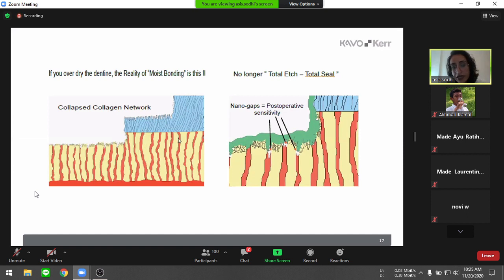It will not percolate. That means that there can be gaps that are left on the dentine surface where the bonding agent has not been able to percolate and seal those gaps. And these nano gaps cause post-op sensitivity, right? So this could be avoided. In a total etch technique, it's important that the doctor does not apply too much pressure while they're drying the dentine surface. And dentine etching is the primary cause of higher post-op sensitivity if the technique that the doctor follows is not correct, right? If they apply a lot of pressure and dry out the dentine too much, that can cause collapsing of the collagen fibers. And then when they apply the bonding agent, it is not able to penetrate, and there are gaps that are formed which can cause post-op sensitivity.